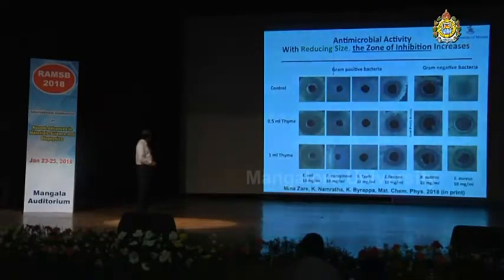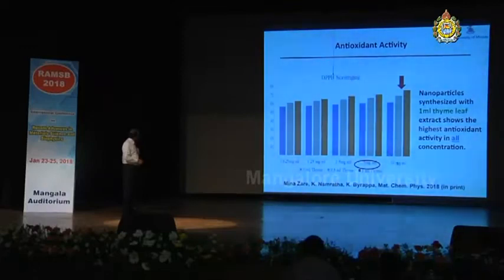And we have tested with these two samples of zinc oxide to see how the zone of inhibition increases with the particle size of the zinc oxide. So the zinc oxide particle size can be reduced by the appropriate concentration of the thyme leaf extract. And here it is shown for different concentrations: 0 thyme leaf, no extract, and this is a biomolecule, and 0.5 milliliter and 1 milliliter of thyme leaf.